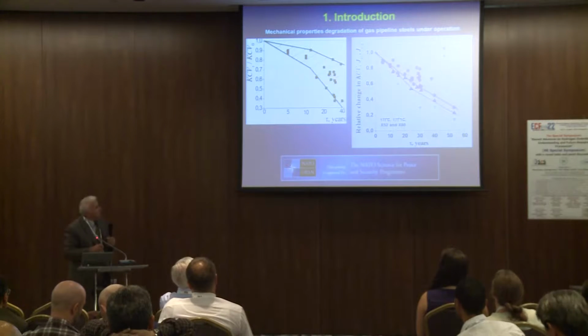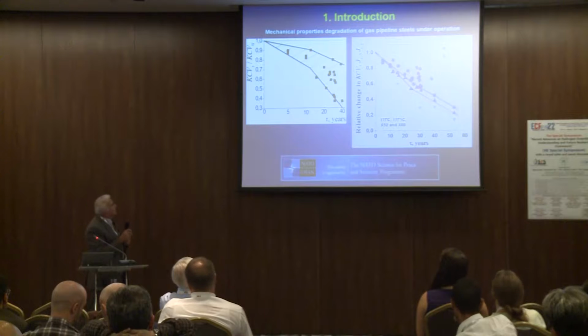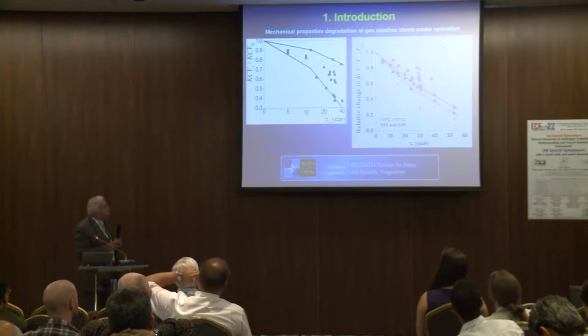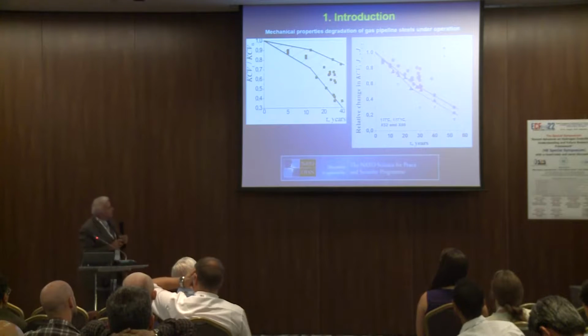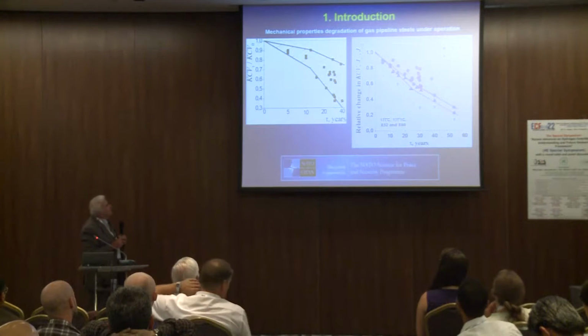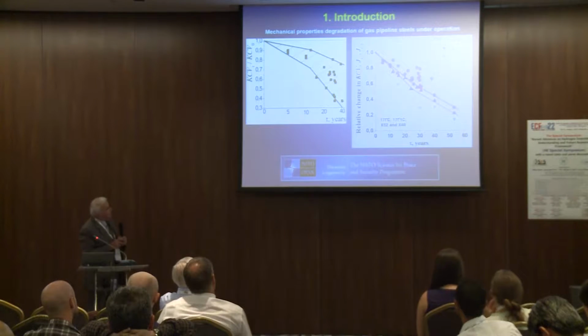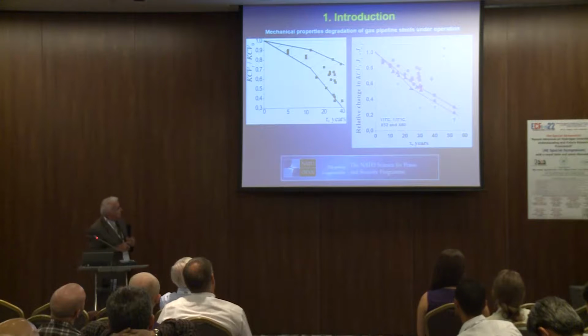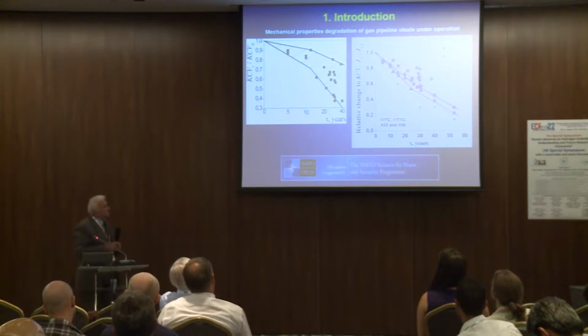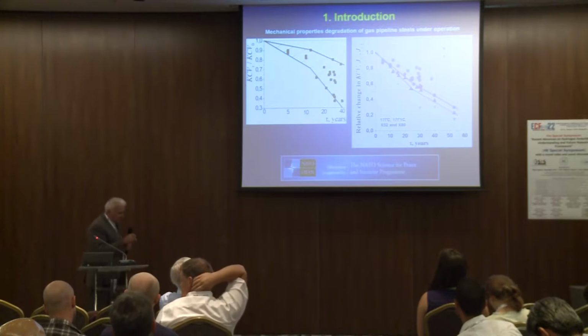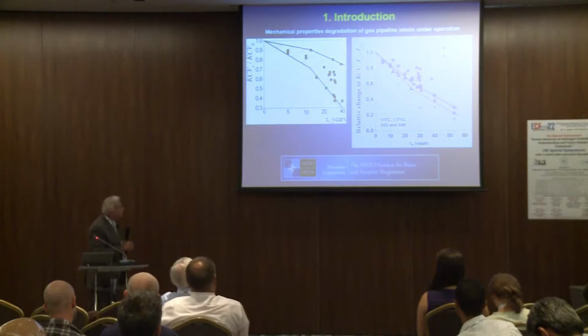Here you can see on the left figure the decrease of impact strength during service up to 40 years of gas pipeline, and you can see a very sharp decrease. On the right figure you can see an additional strong decrease of fracture toughness, the critical levels of J integral. In both cases these brittle fracture characteristics decrease 5 times in comparison with the as-received state. It is very brittle behavior of the material.